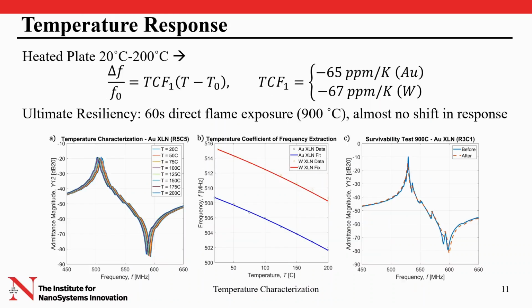Crucial for us is the temperature response. In particular, using a heated plate on our probe station, we changed the temperature from 20 degrees C to 200 degrees C, and we performed measurements in steady state conditions to extract the temperature coefficient of frequency in the linear approximation. It was found to be minus 65 ppm/Kelvin for the gold and minus 67 ppm/Kelvin for the tungsten.